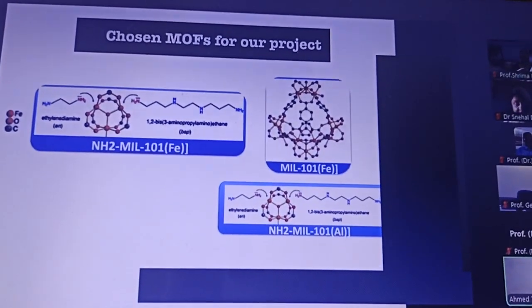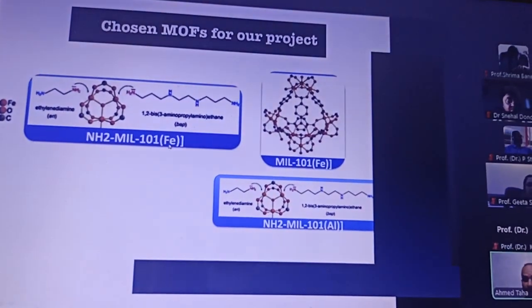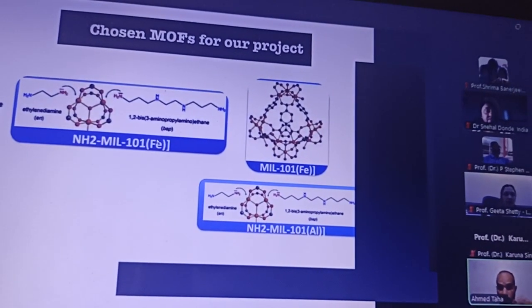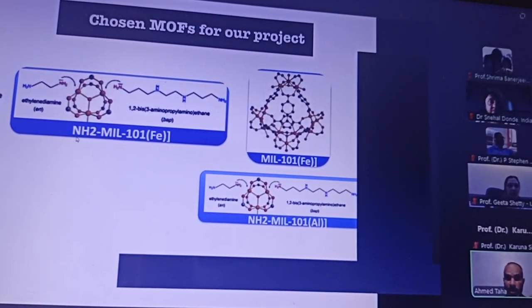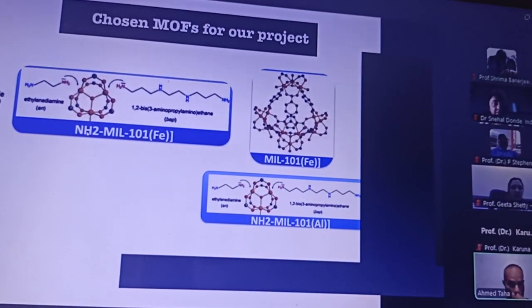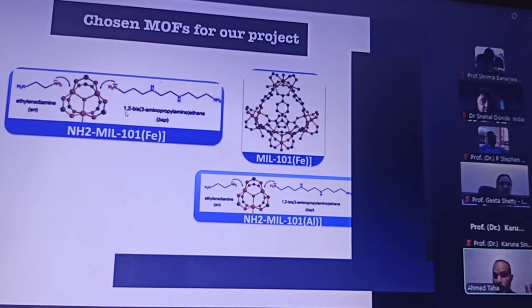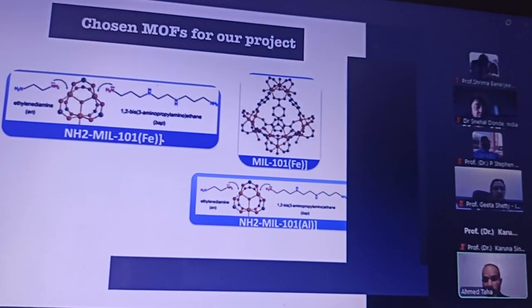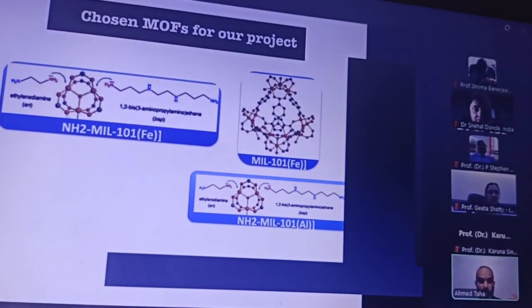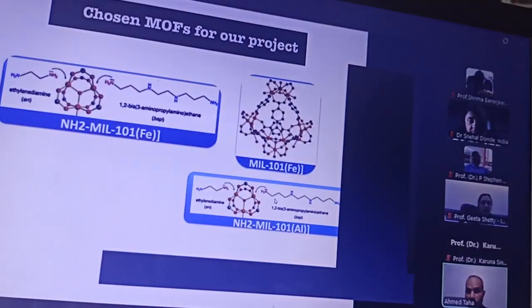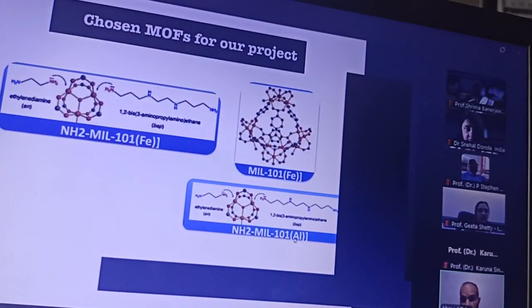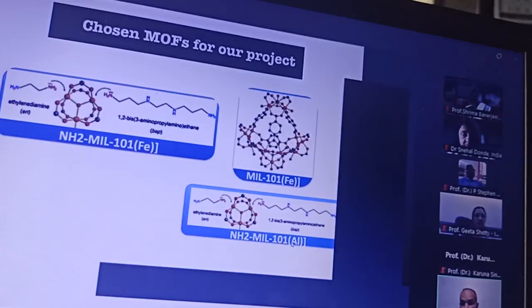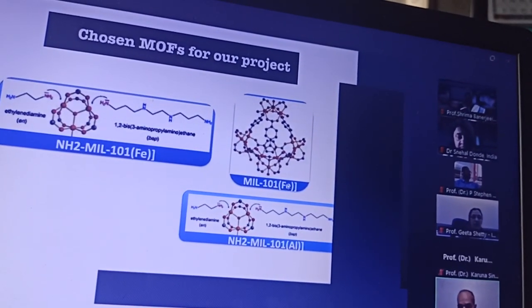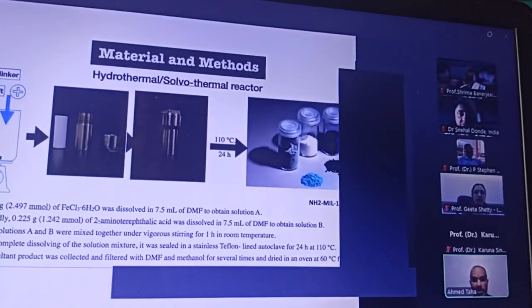So what we try to study here is we have developed one material based on iron, because it's one of the main elements used in the Fenton reaction, and functionalized with amine group. So we have this material with iron and amine group, and to have a benchmark to compare with, we have the same material but without the functional group, the amine group, to know the role of this functional group. And also we have a benchmark material with aluminum, Al, instead of iron, to know the role of iron in this reaction.